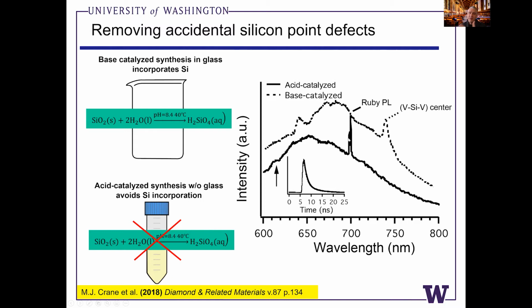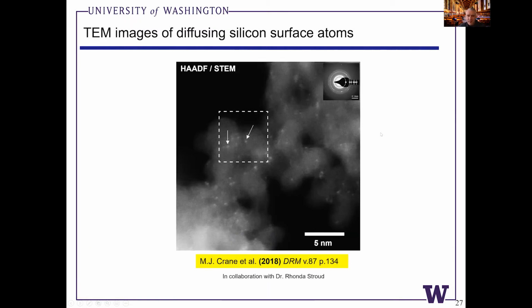This peak here is from ruby. This is the chromium-doped aluminum oxide we use as a pressure sensor. So effectively this emission totally vanished. I have to apologize. This spectrum here is at high pressure, so the NV center is blue-shifted from 640 at high pressure. But just to give a quick overview, we were able to get rid of this silicon in the PL. So we sent our sample to our collaborator, Rhonda Stroud at the Naval Research Lab, and said, Rhonda, we think we've made diamond and we don't think there are any silicon atoms in this at all.